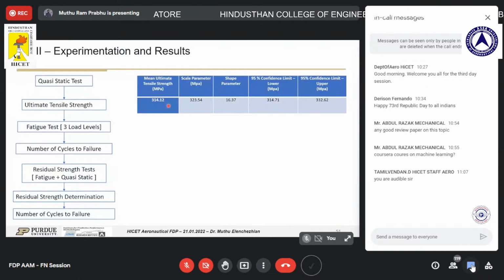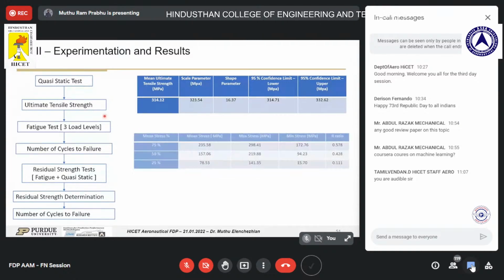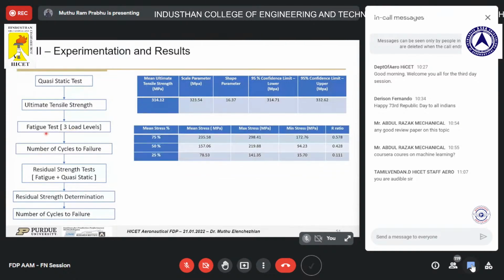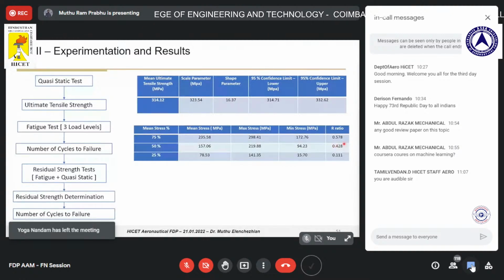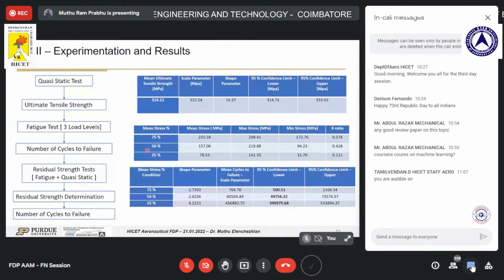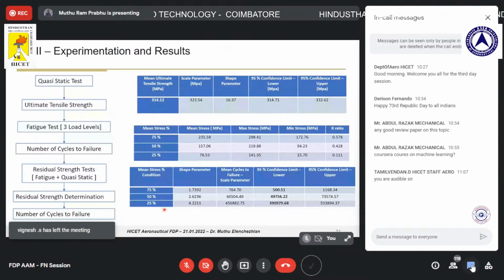314 megapascal, and we did some statistical analysis on what the maximum and minimum values can go to. Based on that, we determined to do the fatigue test at 3 different load levels, that is at 25%, 50% and 75% of the load, with different R ratio values. And for each condition, first we ran a complete test where we collected the number of cycles to failure for each of these different load conditions.